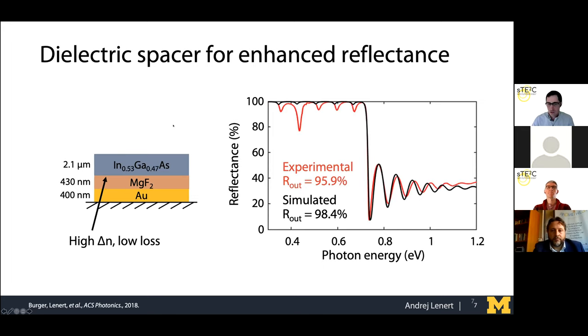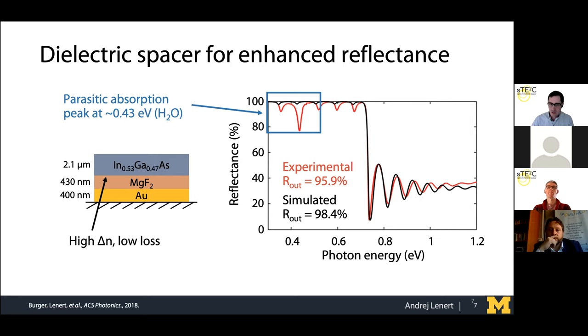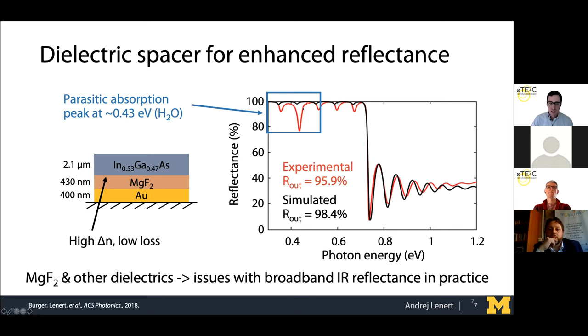However, when we fabricated this layered structure, and this was work that we published in 2018, we were only able to achieve about 96% out-of-band reflectance. And one of the issues that we were dealing with is that water was causing parasitic absorption. And so we were getting deviations from our theory. And as far as we've seen so far, there haven't been any studies that have used the low index dielectric spacer with a lot of success. I think this is related to the issue with eliminating infrared absorption entirely with a dielectric spacer.